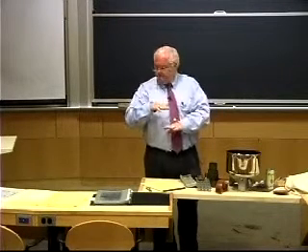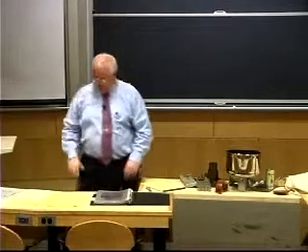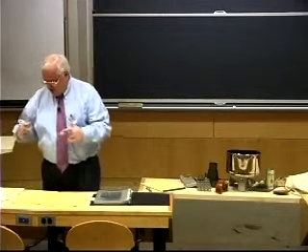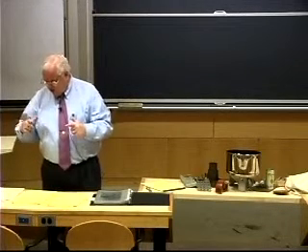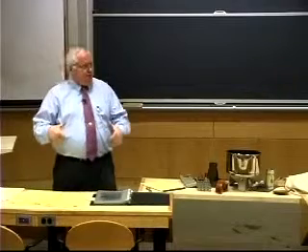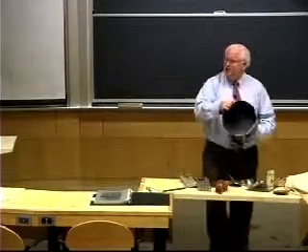Typically, if I remember, I'd have to look at my notes, the largest acceptable flaw for a 6-inch steel plate, which is used in pressure vessels and such, has to fit within a 12-inch diameter circle. A 12-inch diameter circle, that's bigger than this.